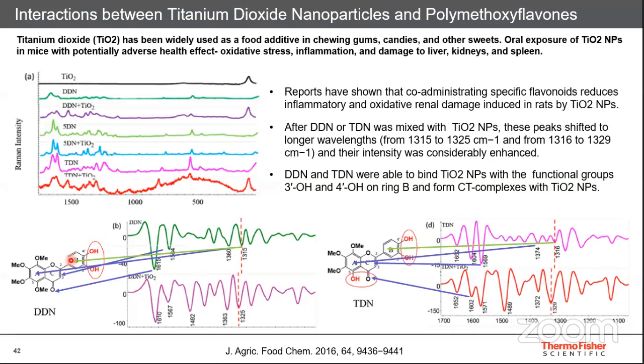So this indicates that the TiO2 material is actually interacting with these two OHs, or this benzene ring with these two OHs, and getting stabilized, and because of which it is showing that reduction in its adverse effect. So this is how that molecule makes it less adverse by interacting with this ring.